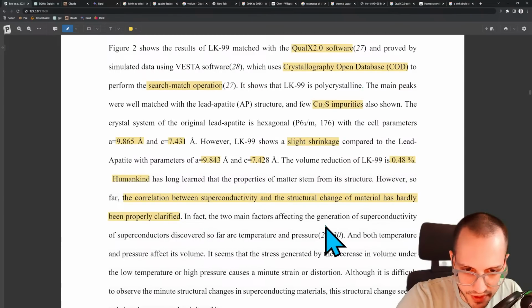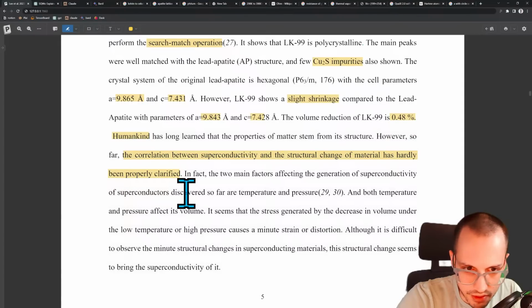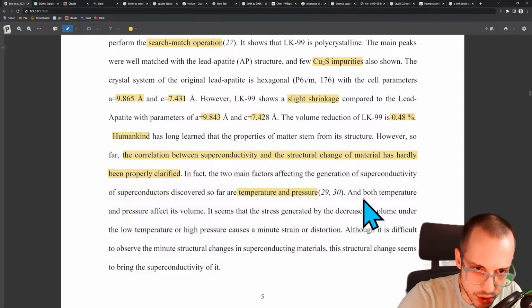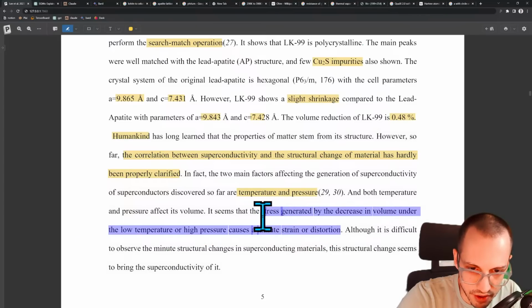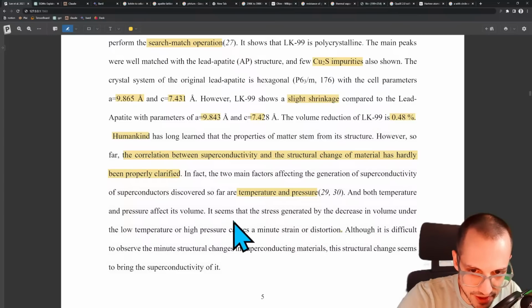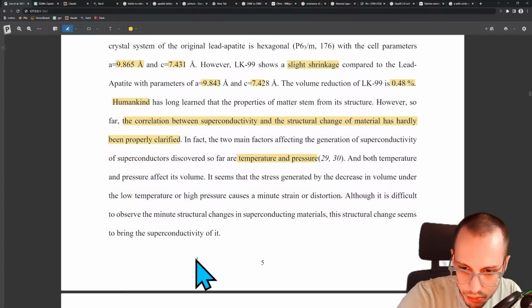In fact, the 2 main factors affecting the generation of superconductivity of superconductors discovered so far are temperature and pressure. So it seems like basically, even though we understood that it's the structure of the material that led to superconductivity, the only way we were trying to get to it was by changing the temperature and the pressure. It seems that the stress generated by the decrease in volume under the low temperature or high pressure causes a minute strain or distortion. All right, so it's all based on this idea of stress on this lattice, and if you can replicate that stress without having to mess with the temperature and the pressure, that's how you get this. Although it's difficult to observe minute structural changes, this structural change seems to bring the superconductivity of it.